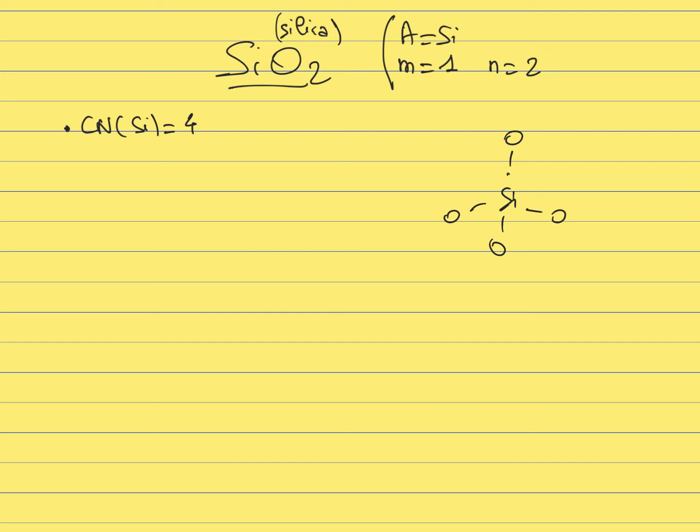The number of cations, M, times the coordination number of the cation is equal to the number of oxygens times the coordination number of the oxygen. This is because those 2 expressions give you the number of bonds within the glass. There are 2 ways to express the number of bonds: the number of cations times their coordination number, or the number of oxygens times their coordination number.